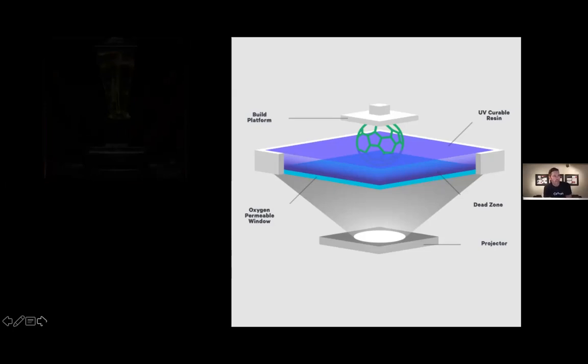Another huge benefit is that when you partially cure a layer of resin and pull it off the glass, and you do that over and over and over again, you're taking microscopic layers off that glass. And over time, that changes the properties of that glass, almost like a lens that's being affected over time. So it'll affect the accuracy of the parts being produced and need to be replaced. And that also does not happen with our technology.